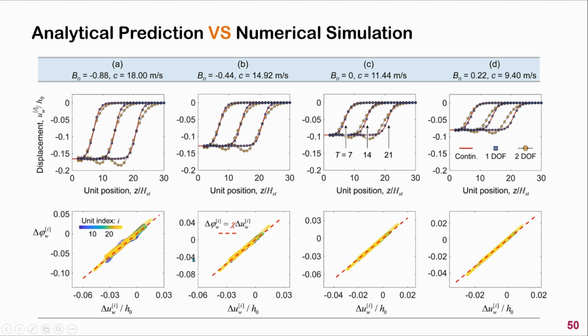In the bottom panel, we examine the linearized relationship we used in building our continuum model. The colored dots are extracted directly from numerical simulation. As can be seen here, all these dots are distributed near the dashed line that corresponds to the linearized relationship between the translational and the rotational movement. And this demonstrates that the relationship we used in building our continuum model is reasonable.